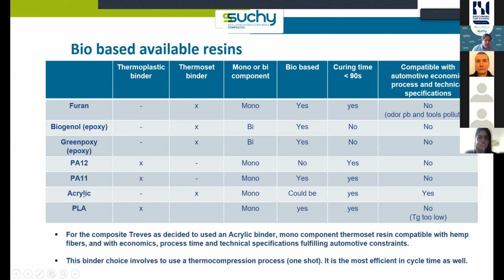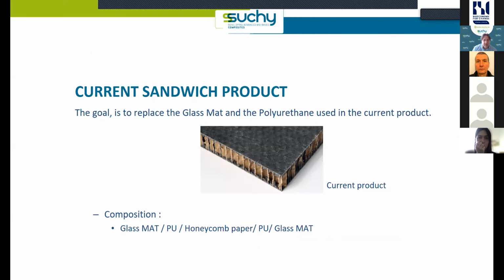That's why we concentrated in the Suchy project on acrylic resin, where we see interesting new features, because there is an increasing content of bio-based components in acrylic resins. There are more technologies available on the market now. So things are moving in a good way from that perspective. So the reference product is definitely what we call Baypreg. Baypreg is now completely dominating the market. I don't know if it's 90% of the load floors that are with this technology, but it should be close to that.